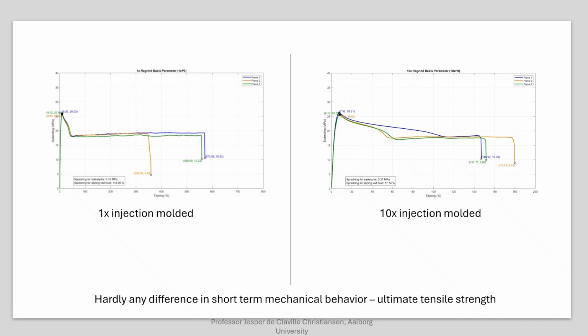Is this important? Not really, because if you design a product, you don't normally design it to be able to sustain an extension at break this much. You design the product not to fail. So more or less, they are very, very similar. There are slight deviations, however, if you look at the top point in the softness just before the yield point. But again, designing a polymer, you do not design it for failure, you design it to not fail. So more or less, you can be happy with the mechanical properties of recycled polypropylene if you experience a short-term load.